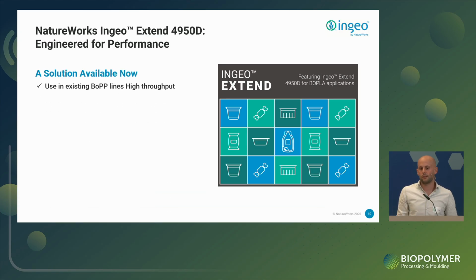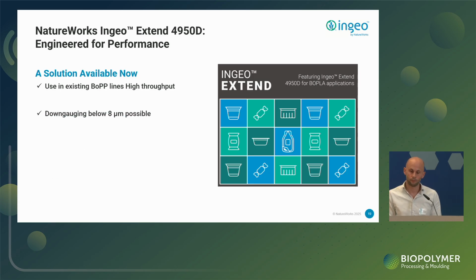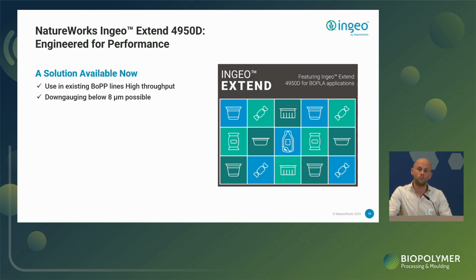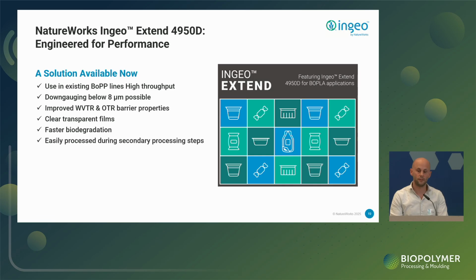So summarizing this, the product runs on BOPP lines with high outputs. We have achieved film thicknesses of well below 8 micron on the recent trial. On the pilot line, we have extruded the material below 5 micron even. And that makes it also interesting for certain lamination processes. For example, if you would combine it with paper and you want to have a very low amount of polymer in the structure, that makes it quite interesting, I believe.